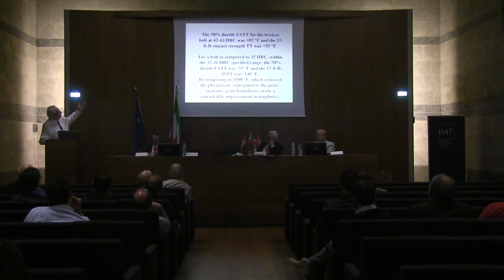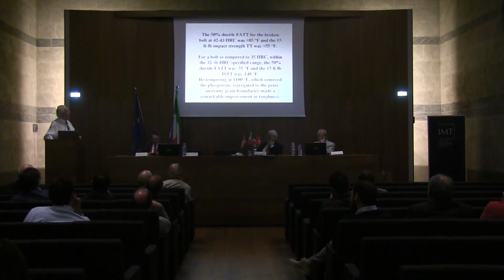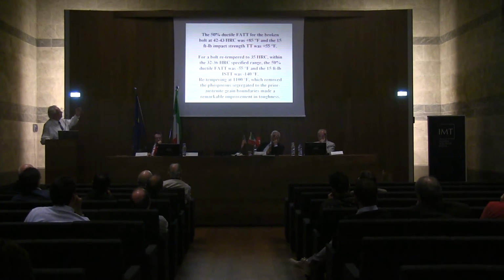So the 50% ductile fracture appearance transition temperature of the broken bolt at 42 to 43 Rockwell C was plus 85 F, and the 15 foot-pound impact strength transition temperature was plus 55 F. That's not very good. For a bolt retempered to 35 Rockwell C, which is within the range, the spec at that time was 32 to 36. I think it's 30 to 36 now.